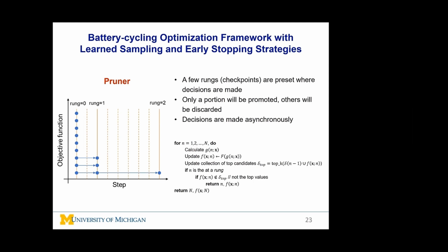The idea may seem simple. However, simply discarding the low-performance batteries in the early cycling stages may cause issues because some of them may actually perform better in later stages. So we developed this systematic strategy to keep some selected low-performance batteries cycling for a certain time so that we do not miss the battery configurations that will perform better later.